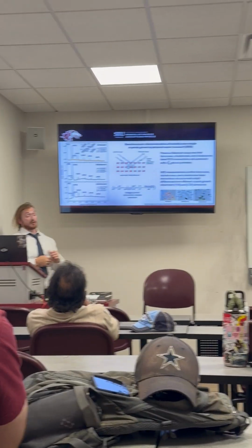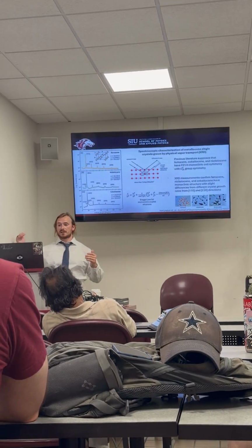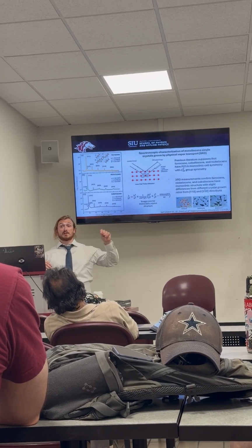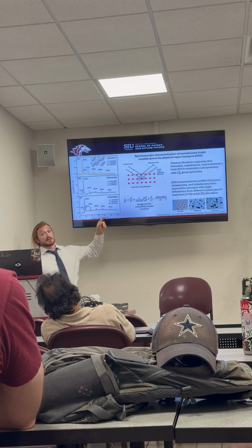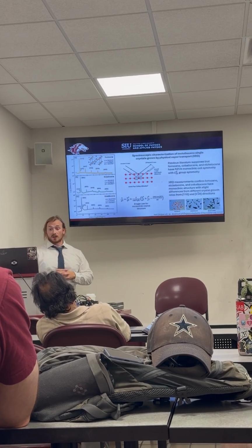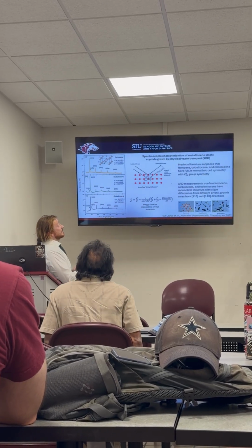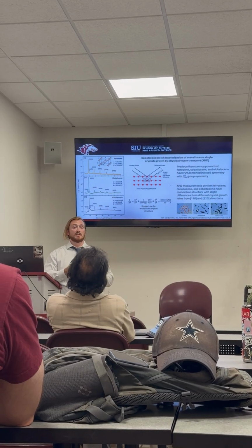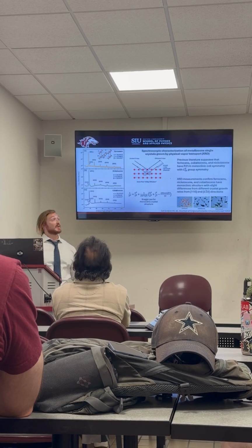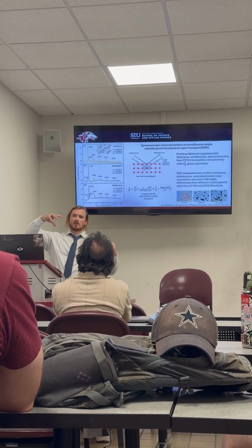Okay. XRD will determine our crystal structure. XRD is the concept that we shine X-rays through the material at a certain angle, and whatever X-rays come back out of that will help us determine the crystal structure, like the plane spacing, also the lattice constants of our crystals. These crystals are grown in a particular monoclinic type of structure. Monoclinic meaning that the A, B, and C axes are all different, and then the angle in between is not 90 degrees, so it's some offset degree. So think of like a rhombus kind of tilted.